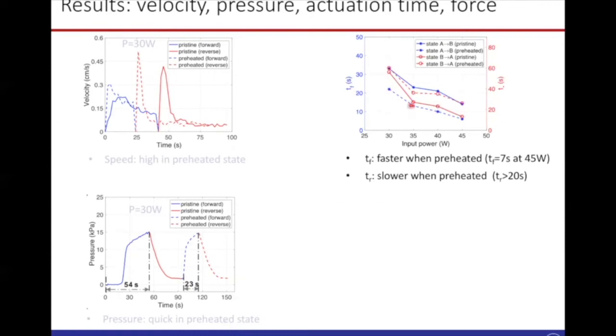So here we show the time of forward actuation. In a preheated state, it gets faster when you increase the input power. At around 45 watt input power, it took only 7 seconds to produce the large transformation. For such a big structure, 45 watt power could be considered small, and it uses around 20 to 22 volt and 1 point some ampere current to actuate. Of course, reverse actuation is a little bit slower because we rely on passive cooling. It requires an active cooling system to speed up the reverse actuation. But even 20 seconds is not very bad actually.